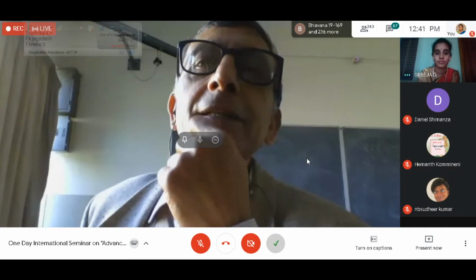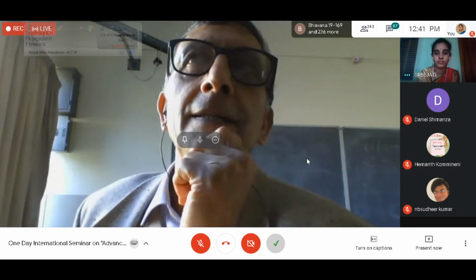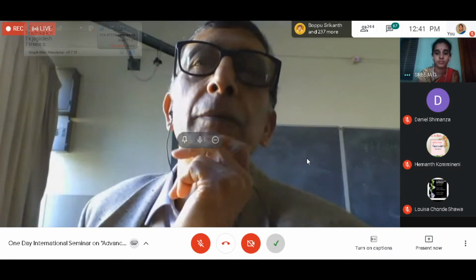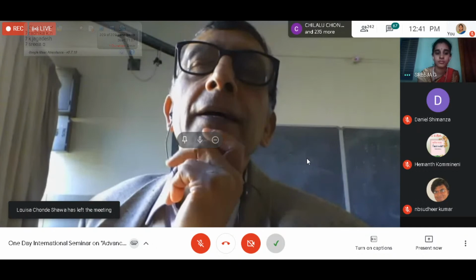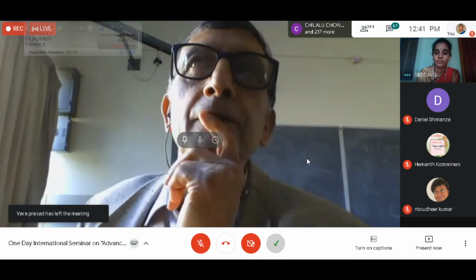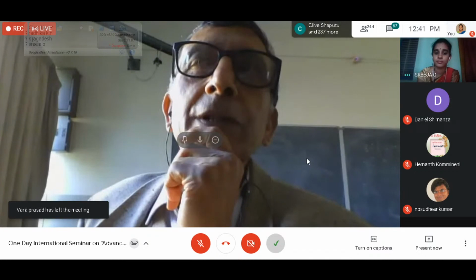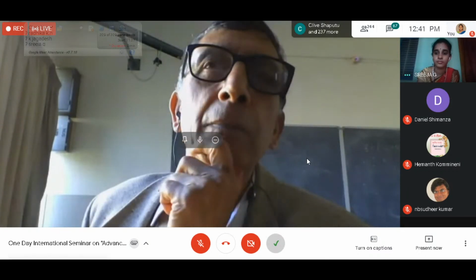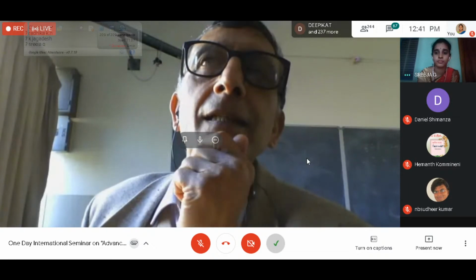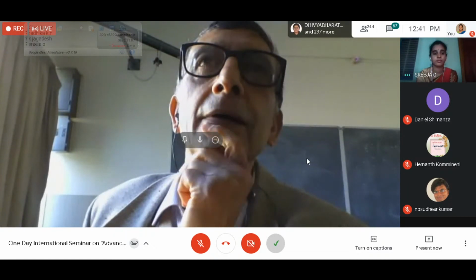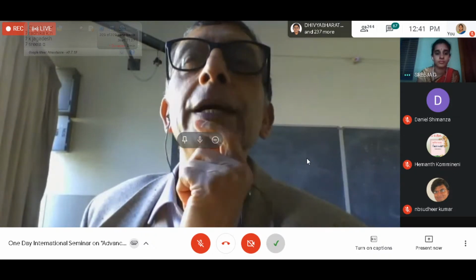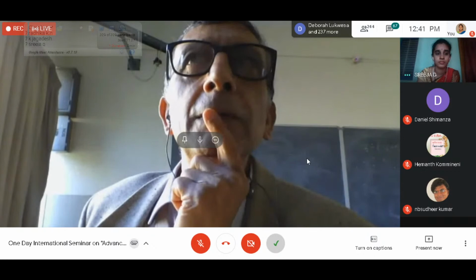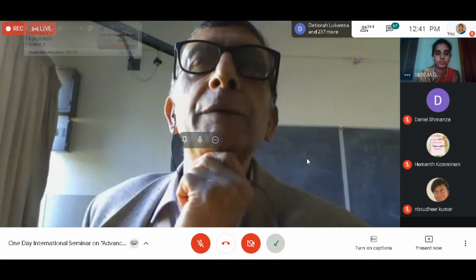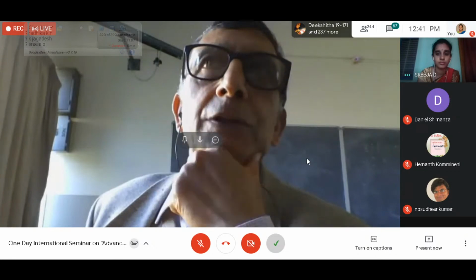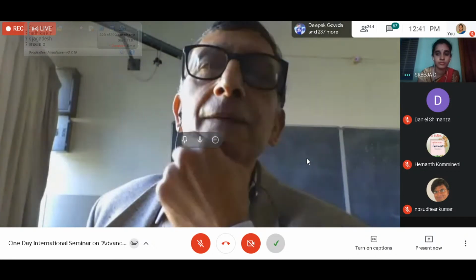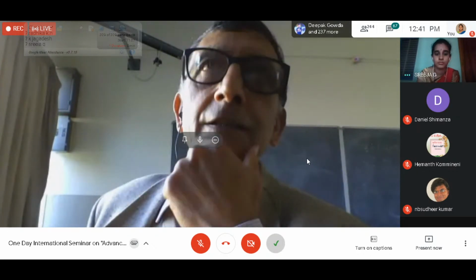The animation that I showed you raised the concrete temperature from 20 degrees C to about 52 degrees C. And that took, in that animation, about 15 days. The rate at which that heat will be lost to the outside is actually much, much longer. So you get a fairly steep heat curve initially and a much shallower cooling curve. I wouldn't try to stop heat from moving between successive layers. In some ways, it is beneficial because it minimizes the temperature difference. So the upper layer almost has an insulating effect.